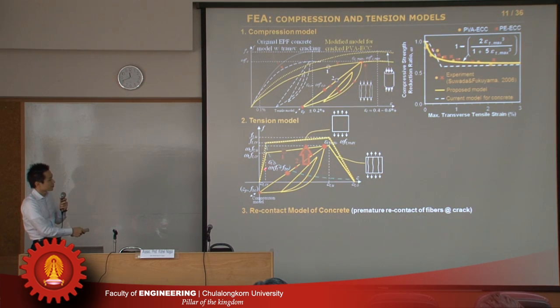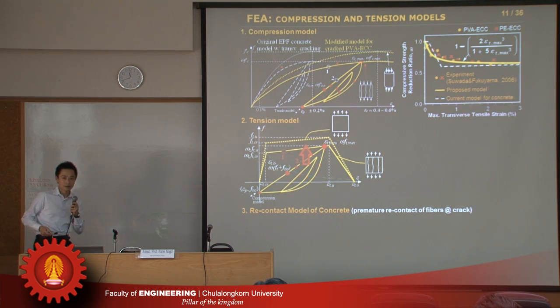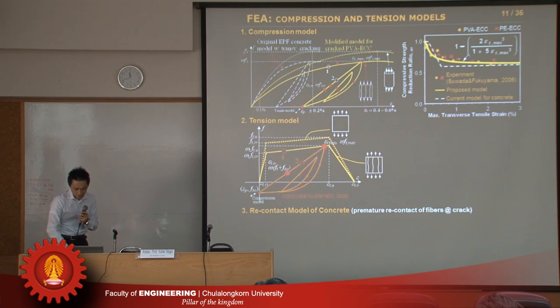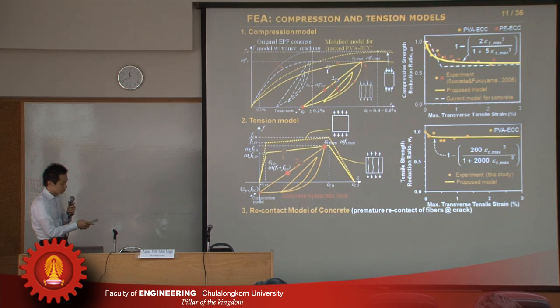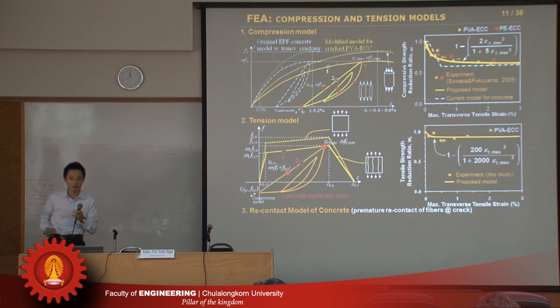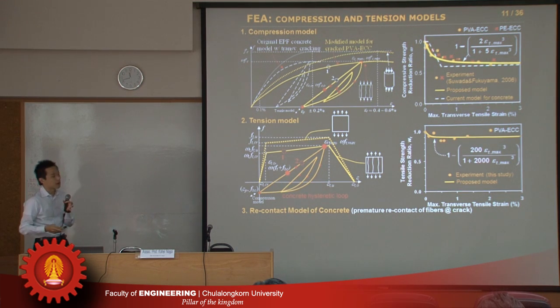So we adapt the trilinear line for the failure envelope like this, and we select some unloading and reloading curve. Actually, I will show in the next slide the verification of this unloading and reloading curve. But anyway, yes, we have unloading, reloading, and also due to the lateral cracking, I mean, when we have the crack orthogonally to the loading direction, we have a reduction of the strength, as I said. We develop some equation to express that effect. It means once we have damage in the lateral direction, compression and tensile strength reduce according to the damage level in the lateral direction. Yes, in compression also we have.